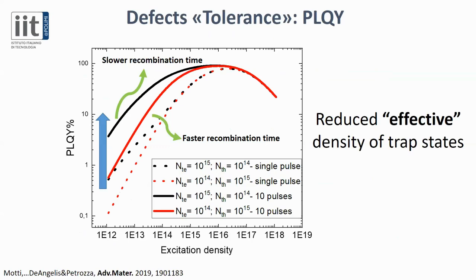So you excite with photons, we see how many photons are getting out. The dotted line here is the photoluminescence quantum yield if we consider only the trapping rate of carriers. The red lines belong to a situation where we have an excess of hole trapping states, the ones with very fast dynamics. The black ones are a situation where we have an abundance of electron trapping states, so the trapped carriers have a very long lifetime.